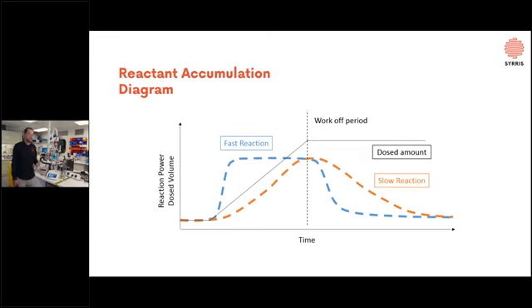To understand a little bit more, I have this small diagram. If you look at it, there are 3 lines. The black one is the dosed amount. If we talk about the fast reaction first, on the onset of dosing we have a reaction power increasing, and as we stop it, it will decline quite fast back to the baseline. With the slow reaction, you can see when we stop the feed, it's basically just about when the reaction power reaches its maximum. And even if we stop the feed, it will take a long time for the reaction to work off back to the baseline, because we have a large amount of reactants present inside the reactor.